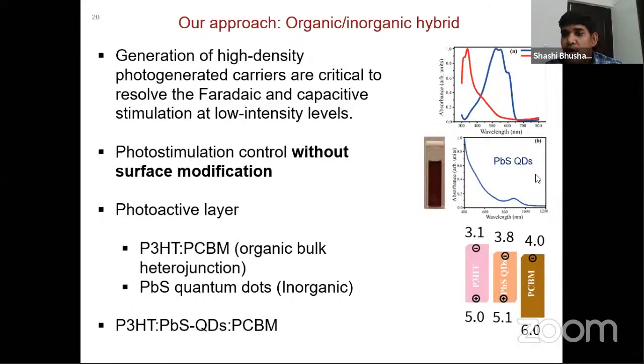However, if you use the PbS quantum dots, which have been successfully demonstrated by the solar community, the PbS quantum dot has very much potential in improving the efficiency of solar cells. With the PbS quantum dot, people are now getting more than 10% efficient devices. By mixing these two, we can see that there is a band alignment. If you mix in PbS quantum dots in an appropriate quantity, there will be a band alignment which supports electron transport towards one side and hole transport to the other side. So these kinds of specific properties we utilized for our device.